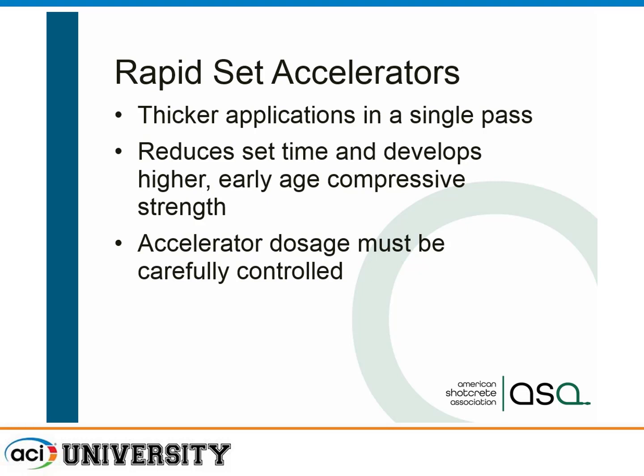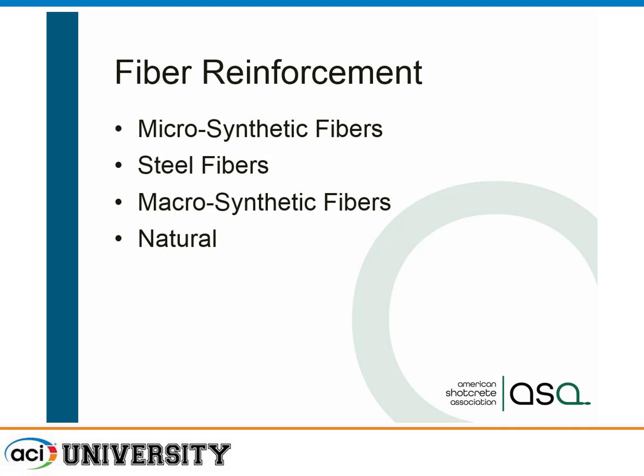One thing, if you do have a job that's using accelerator, be very careful. Too much accelerator is a bad thing. Too much accelerator will make your concrete less strength long term. You know, there's some superintendents that say more is better, and maybe it might set a little bit faster, but it really does significantly affect the strength. So you need to be sure that it's very closely dosed in the volume of concrete going in place.